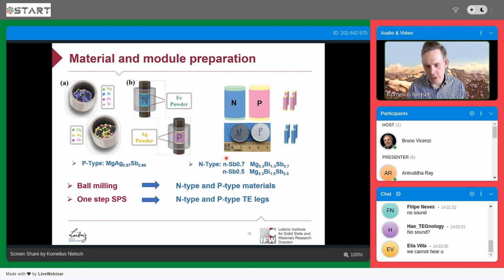The technique we are using is quite scalable. It's mechanical alloying by ball milling. We just take the elements, put them in a ball milling jar, and let it run for a number of hours. Then we use, for example, spark plasma sintering to compact the material. To optimize the contact, we usually directly compact the contact material with the main thermoelectric material. This makes the whole production even more efficient by using this one-step SPS process where we combine the thermoelectric material with the contact material.